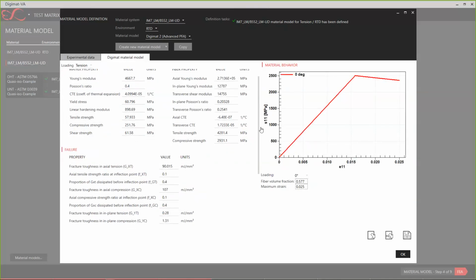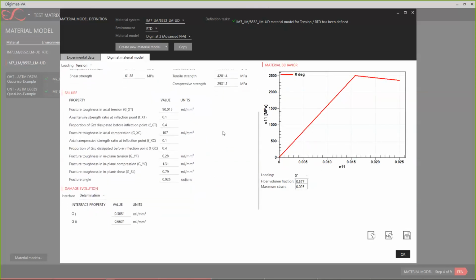And then another additional parameter now needs to be defined. Those parameters are related to the damage propagation law, and that's where the user will have to define the intralaminar fracture toughness: in axial tension, in axial compression, in plane tension, in plane compression, and in plane shear.